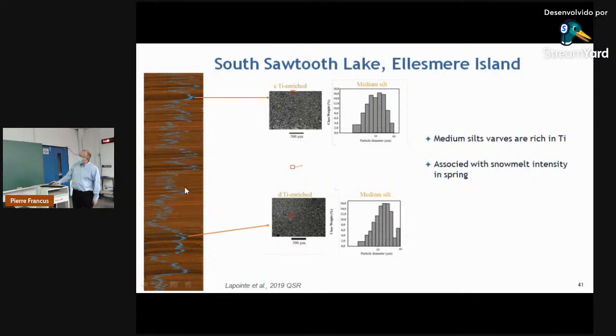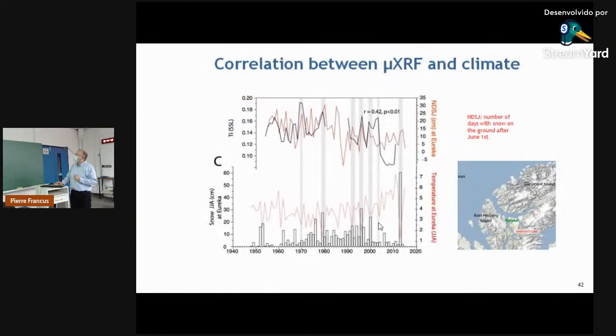And here on the left side, you have the sediment core with, on top of it, the titanium profile. And I told you the titanium is usually indicative of detritic elements. Basically, when we do very precise analysis of these peaks in titanium with an image analysis and scanning electron microscope technique, we can measure the grain size, and these peaks of titanium are really linked to the amount of medium silt. They are indicative mainly of medium silt. And the medium silt is associated with snowmelt intensity. That's also something I mentioned earlier.